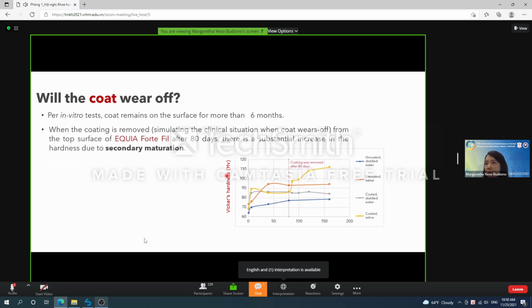So as you can see from the chart here, the orange line indicates the material that was placed inside saliva, but without coating agent. Of course, there's an increase in the hardness of the material, but afterwards, it just stays flat. It was going on stagnant. But it's very different to the material that was coated at the initial period.